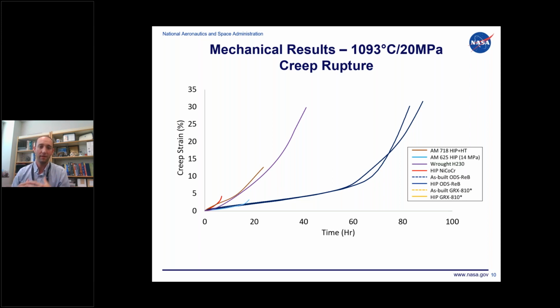So overall, all these nickel-based alloys really can't handle this type of high temperature, and the part fails very quickly. This blue curve here is one of our original ODS alloys that we produced, which we were very excited about because, hey, we doubled the life compared to Haynes 230 with this ODS alloy.